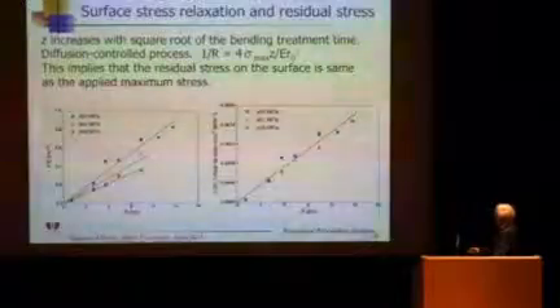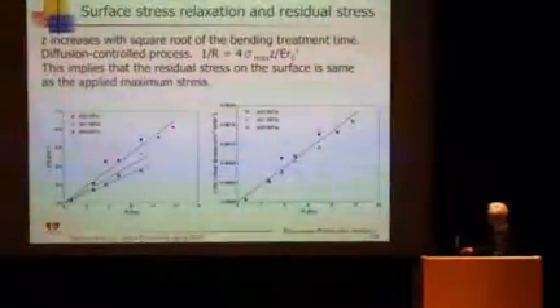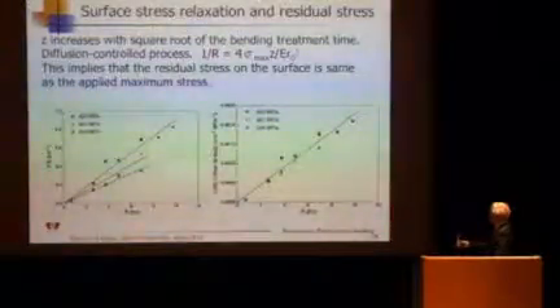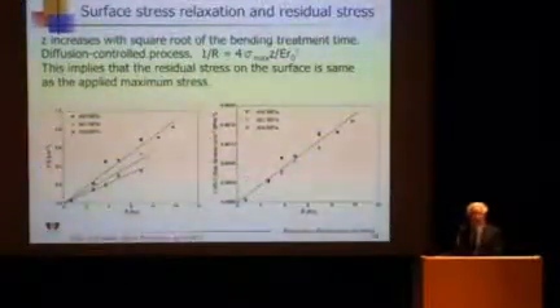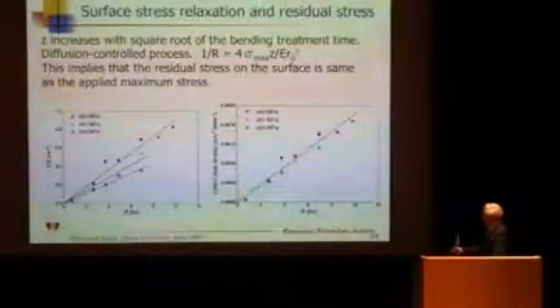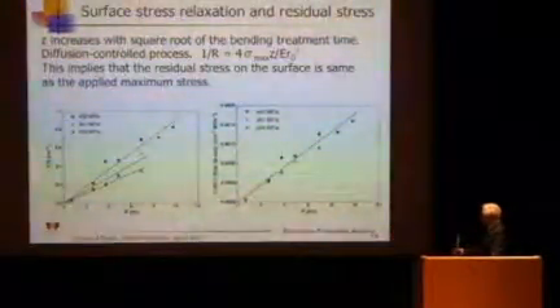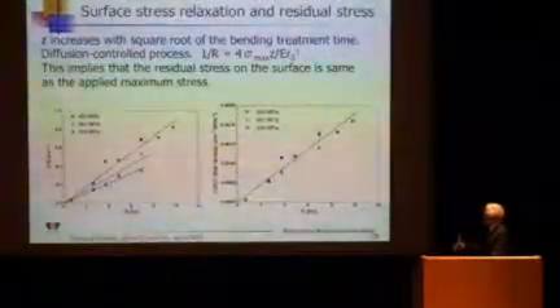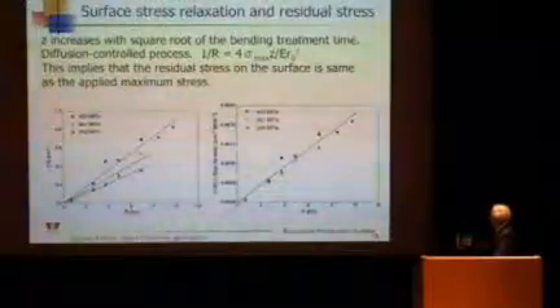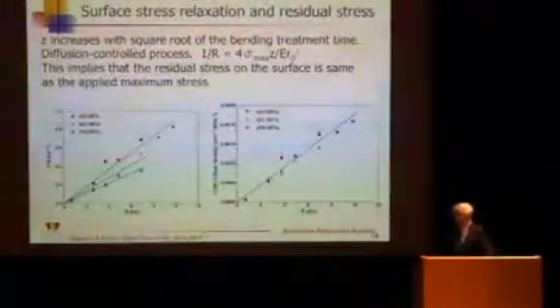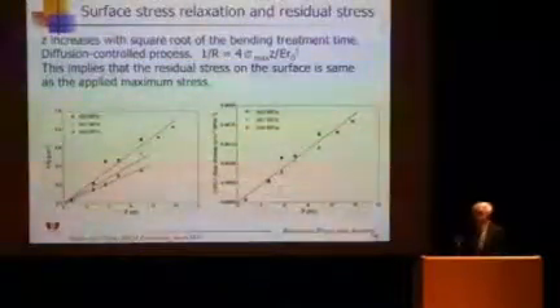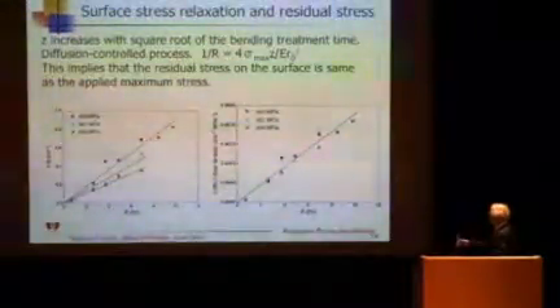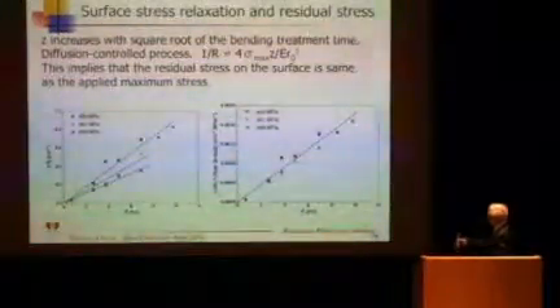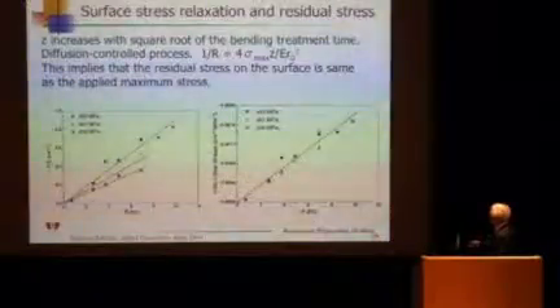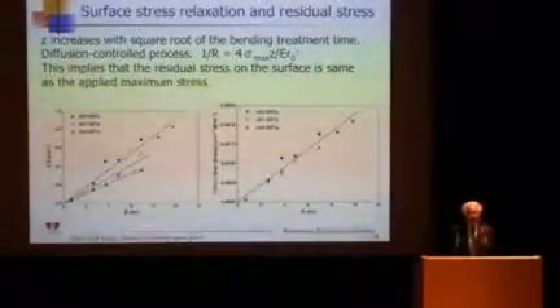And so we did this as a function of time, square root of time, and the change of curvature. The equation suggests that if it's a diffusion-controlled process, the radius of curvature changes with 1 over square root t. Sure enough, with the experimental error at various different stresses, you saw the bending kinetics following the square root of time. So a diffusion-controlled process is taking place. And if you normalize the different stresses, divide by stress, we get superposition of all this data. That suggested to me that the surface layer relaxation is almost instantaneous.